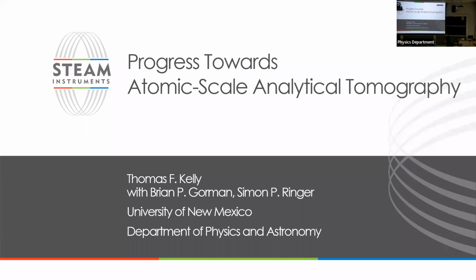And we get to the late 90s, early 2000s, and I started working on the local electrode atom probe, and we got that idea working. The large field of view instrument at Oxford collected atoms at 1 atom per second, which at the time was great, but think of it, 1 million atoms takes you 12 days to collect. And 1 million atoms just does not matter much. You'll see some images today that are much bigger. We were able to develop the local electrode atom probe and get 10,000 atoms per second. So we got a 4 orders of magnitude increase in speed, and that's what really made the atom probe a practical tool.